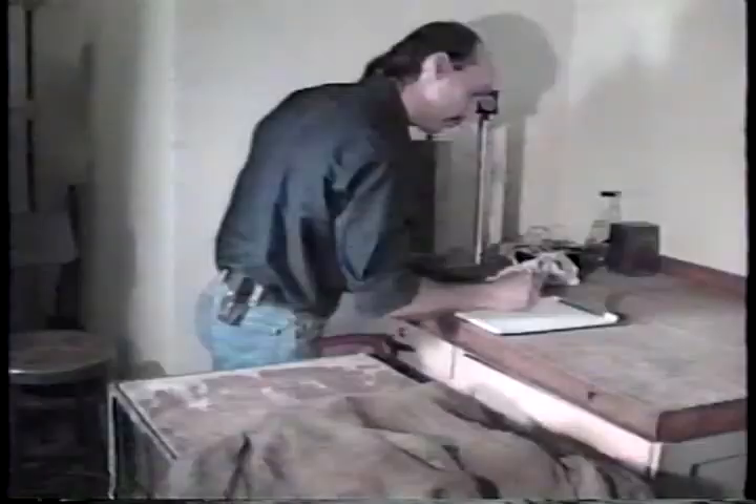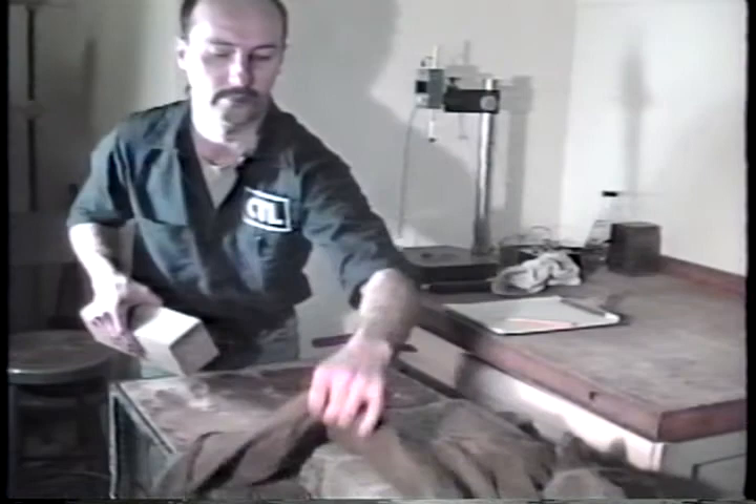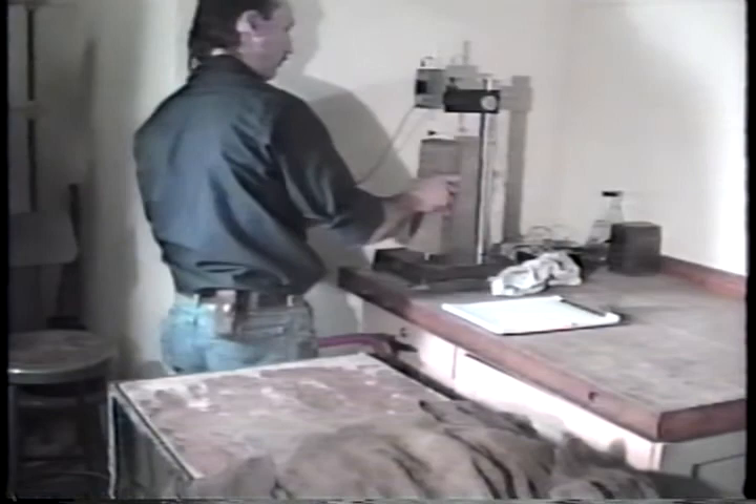If you're following the length measurement option, an initial length measurement should also be made. Damage during testing will be reflected by an increase in length. These expansions, however, are very small — only three hundredths to a tenth of a percent — so be very careful making this measurement.